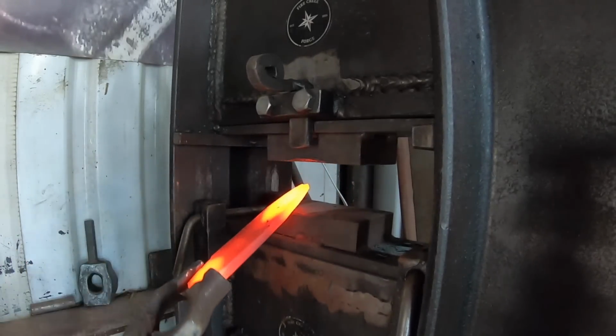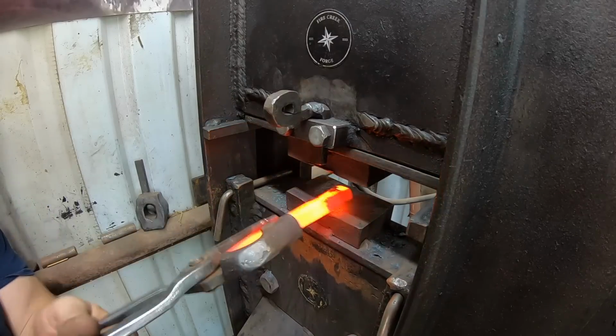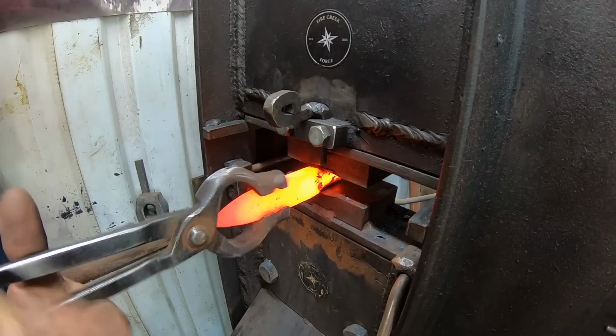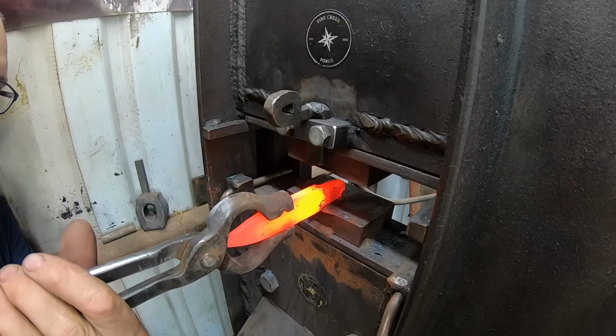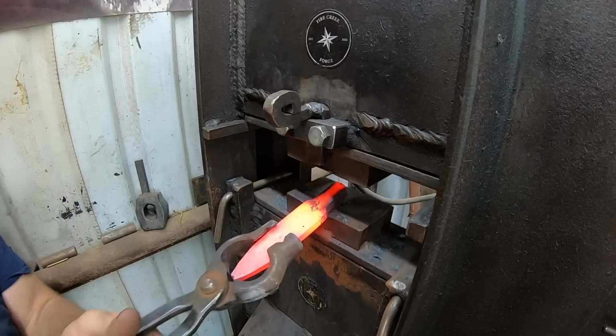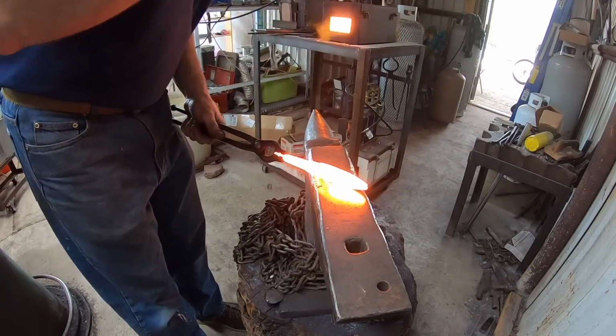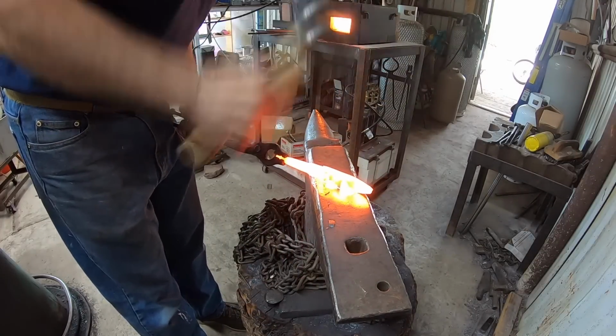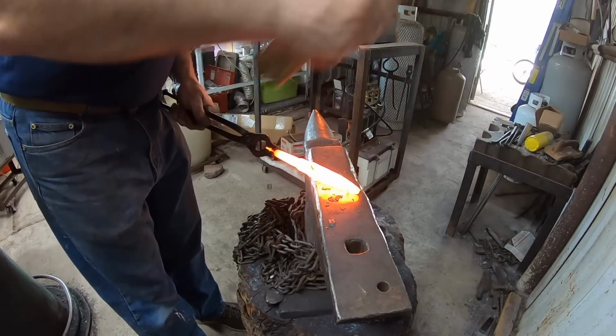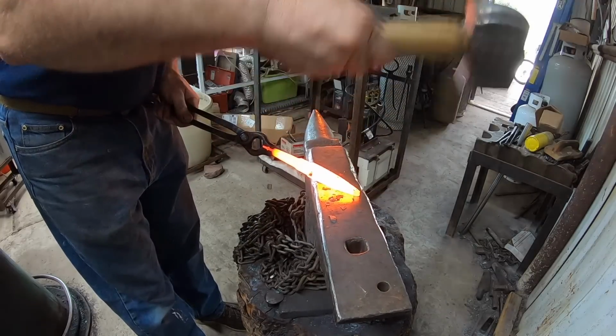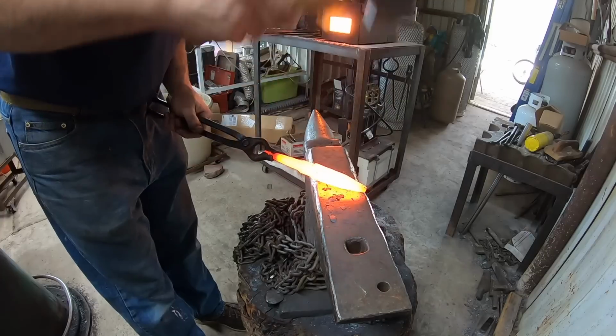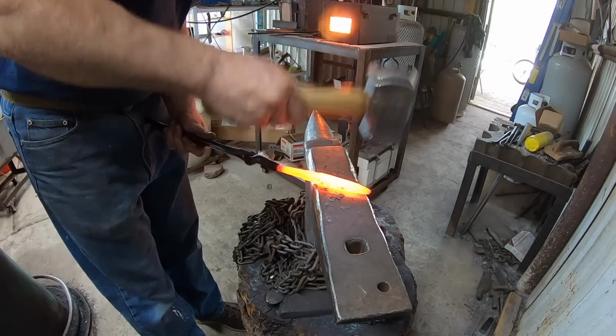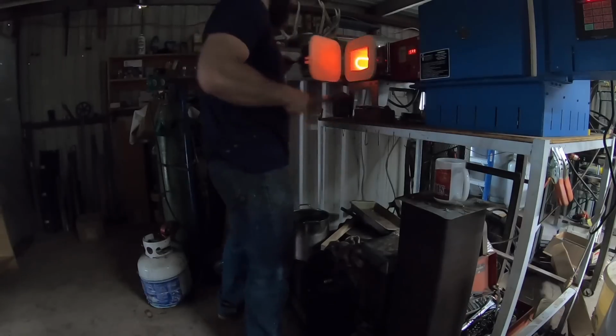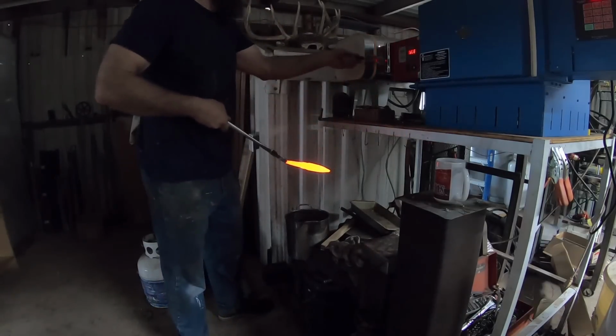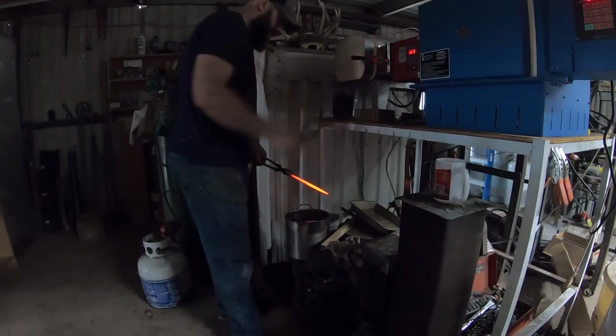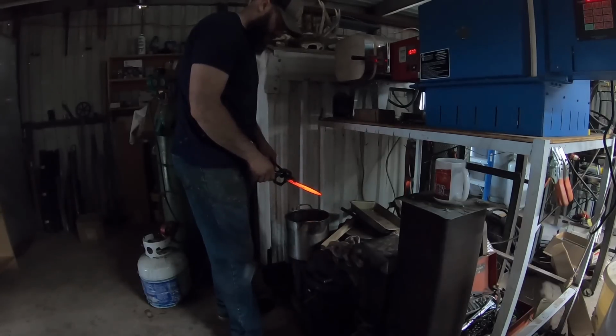You'll notice that I'm not forging the bevels on this dagger here. We will just be doing the profile, which includes the tang, and leave it at that. The reason for this is since you have 4 bevels involved in a finished dagger, it can be a bit of a challenge if you forge and or grind the blade partway and then go into the heat treat. Any kind of warping or twisting that presents itself is more difficult to deal with when you have 4 different bevels you're trying to line up.